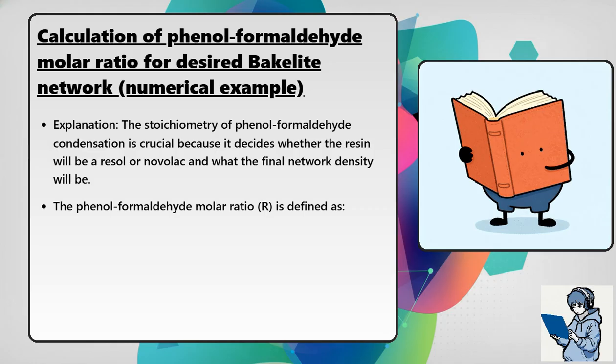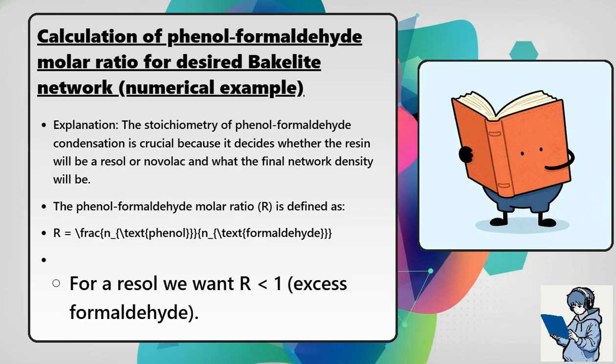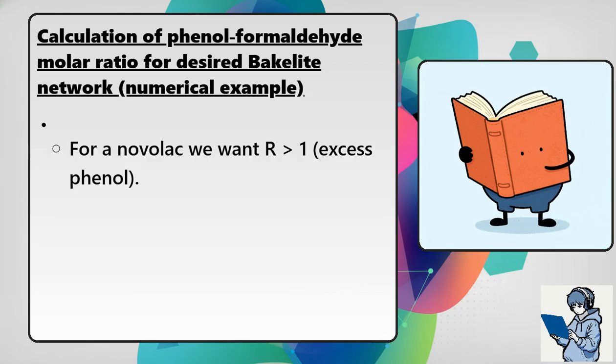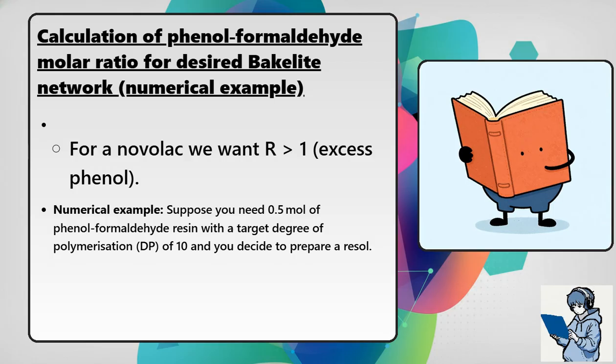The phenol formaldehyde molar ratio, R, is defined as R equals N phenol divided by N formaldehyde. For a Resol, we want R less than 1, excess formaldehyde. For a Novolac, we want R greater than 1, excess phenol. Numerical example: suppose you need 0.5 moles of phenol formaldehyde resin with a target degree of polymerization dP of 10, and you decide to prepare a Resol.